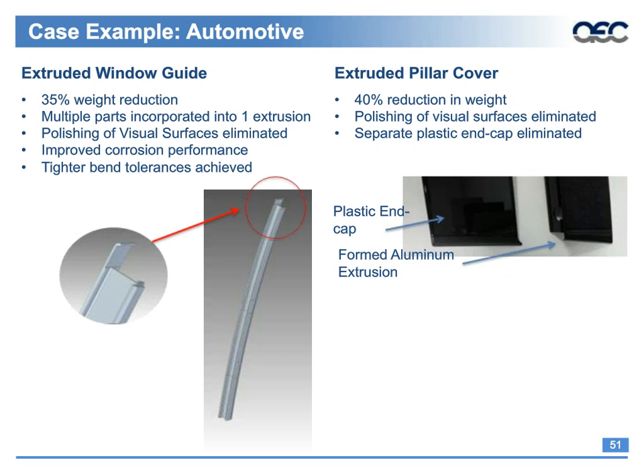It was a high visual requirement. The roll form steel parts that were there before needed to be buffed before painting, and they were too heavy. So the result is a 35% reduction in the window guide and 40% reduction in the pillar cover. And you have a much better looking, lightweight part. These parts also have a nice bend to them, as well as if you look in the circle on the left-hand side, it's rolled over to help the contour when it's assembled onto the car.